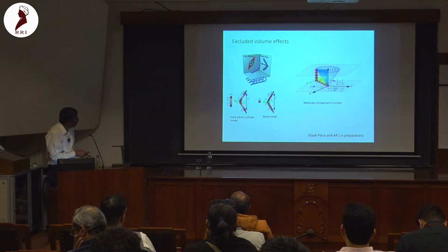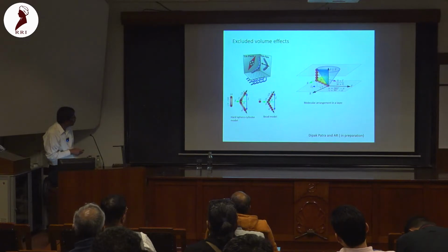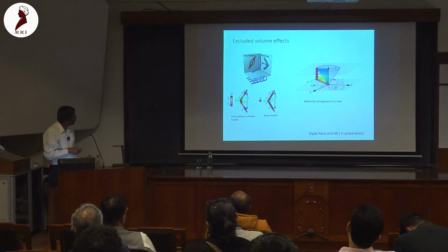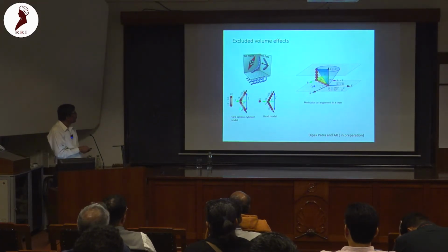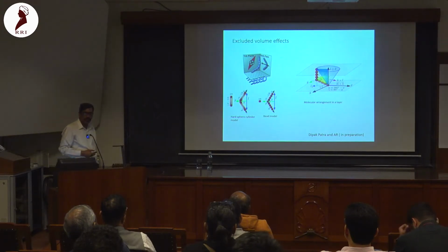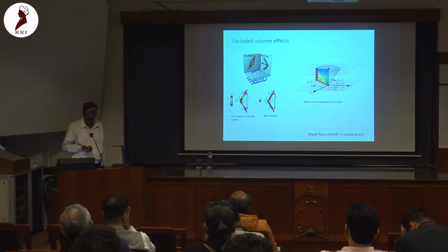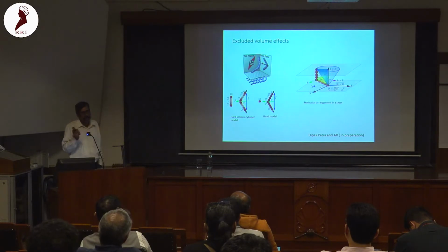So here the molecule is modeled as a set of beads connected like this, of diameter 2r, and this bent-core molecule is modeled as two spherocylinders joined end to end with an angle beta, and the physics is very sensitive to beta. When beta goes to 180 degrees, it becomes a linear molecule, and a linear molecule has very different phases from this. Between 120 degrees and 90 degrees, there is a large change, but between, let's say, 140 and 110, it is less sensitive.